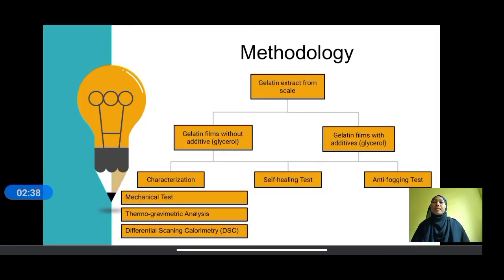This is basically the method we use to study this gelatin-based film, in which we extract the gelatin from the scale and transform it to gelatin film without additive and with additive, and we characterize it by mechanical test, thermogravimetric analysis (TGA), differential scanning calorimetry (DSC), self-healing test, and also antifogging test.